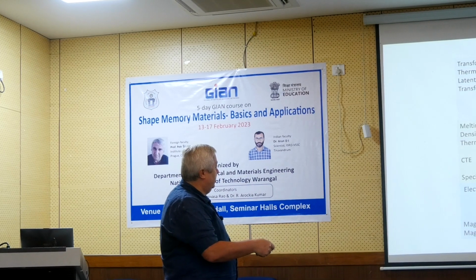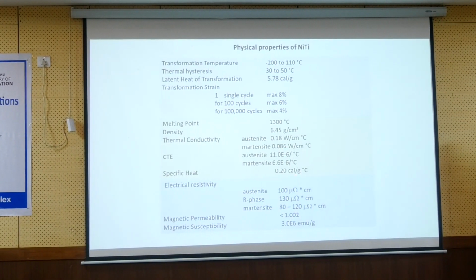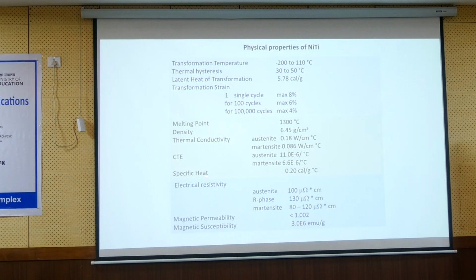Then some physical properties, which I don't have to discuss much. Coefficient of thermal expansion. Well, it is not that different, first of all, and you can divide. This is defined always for a single phase, like in physical tables. Then if you use it simultaneously, you would have how much austenite, how much martensite. It is very important in shape memory polymer composites, because you have the austenite wire embedded in the polymer matrix, and then you compare the thermal expansion of the wire and the matrix. And this is different. So when you cool such composites, depending on the CTE mismatch, you might get stresses. So in those applications, this is very, very important.